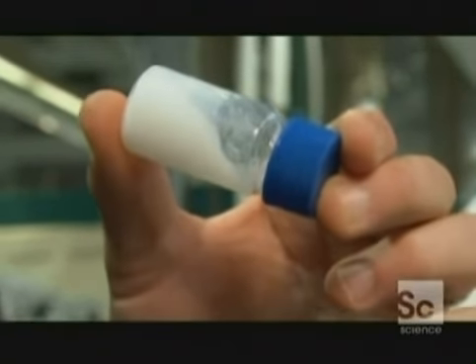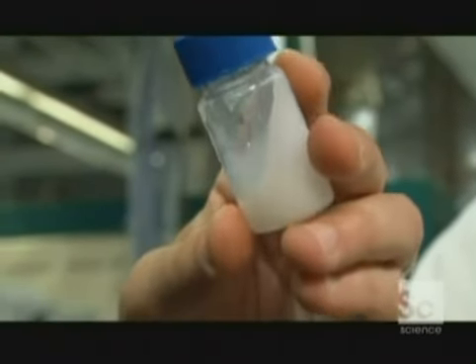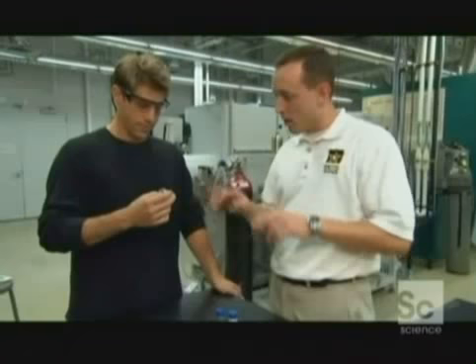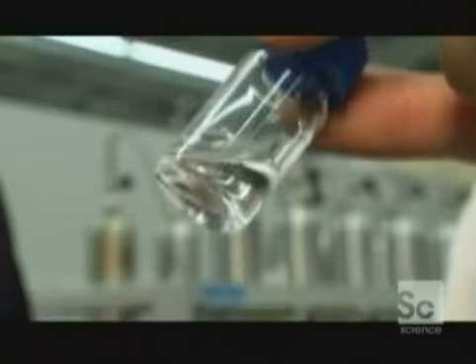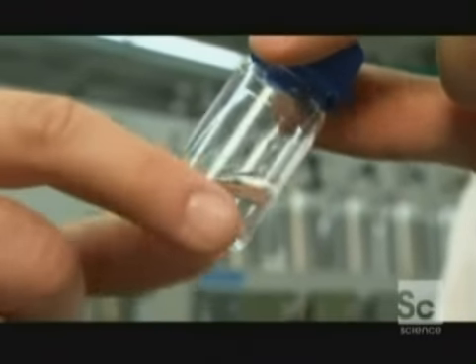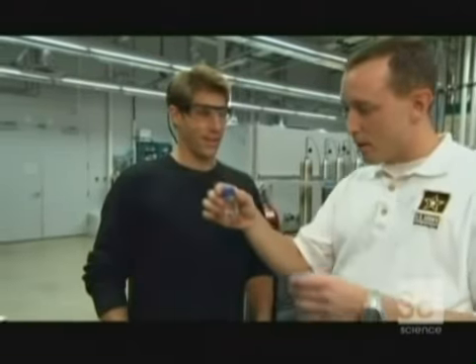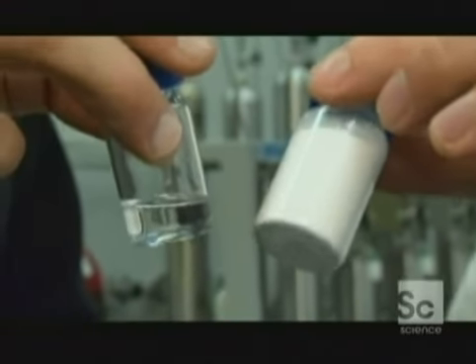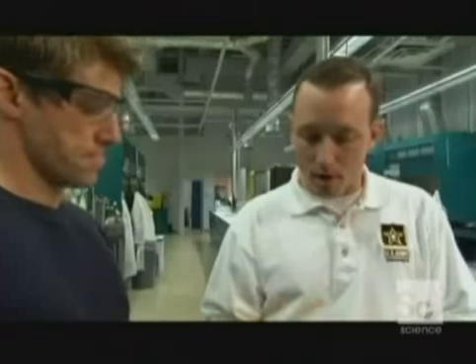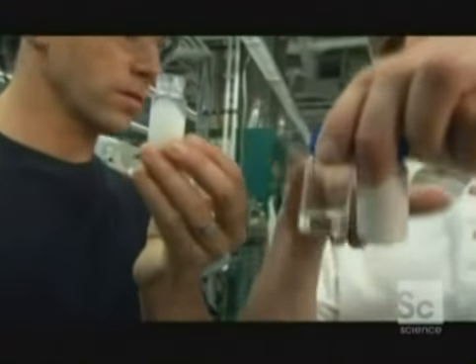This super strong goo is called shear thickening fluid. Okay, so how did you make this? Well, this actually has 2 parts in it. It's a liquid and a solid combined. So the liquid is this thing here. It's called polyethylene glycol. It's a polymeric liquid, very safe. It's kind of like antifreeze, but you could actually eat it. But you combine this with a solid phase, which in this case is a powder. It's silica powder, so silica is glass. But it's very special the way we combine these. This that you have in your hand was actually this amount of liquid mixed with this amount of powder.